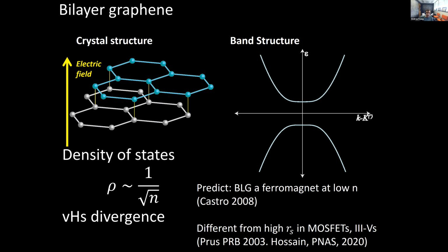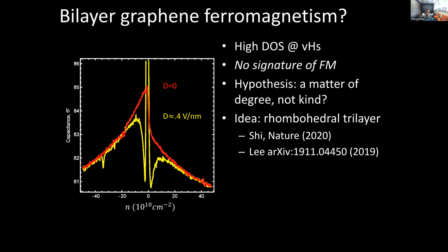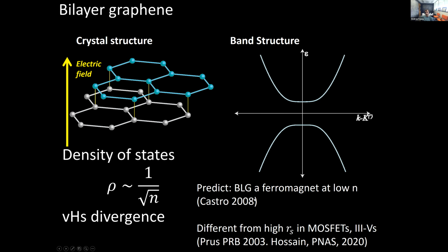And now you get something different, where when you apply an electric field in particular, you're going to get a density of states that actually diverges as you get close to the band edge. So now you have the situation where you have a divergent density of states, and you can hope that in fact you'll get all this correlated electron phenomena, because you're finding a way to artificially increase the density of states and make it large enough that you will get interesting behavior that's not described by a simple single particle band filling picture.